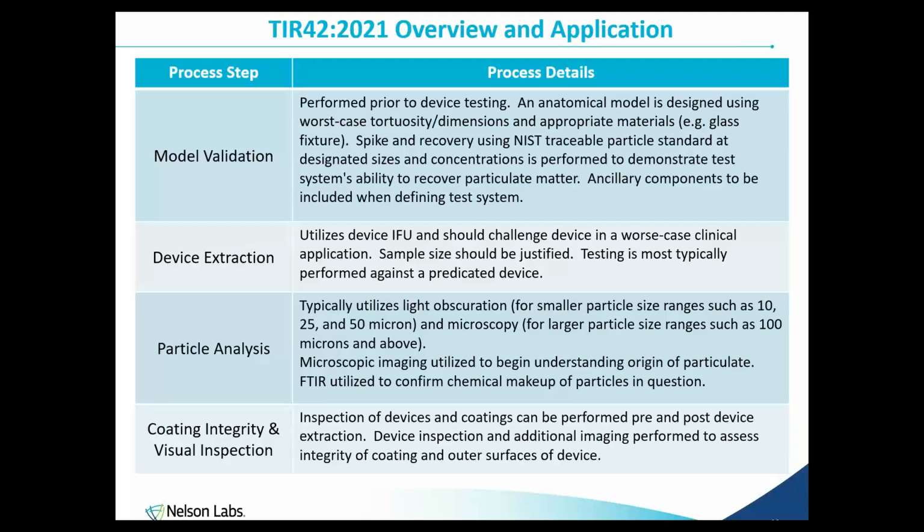that's typically a better way to make sure you're capturing all of those larger, more dense particles that during analysis, if you're using something like a HIAC system, could settle towards the bottom of a collection container. So the microscopic method allows you to capture those larger particles. And then you can go beyond that by performing some imaging, like in the last slide. And at that point, you've isolated the particles on a slide such that you can move on to further identification, so something like FTIR or SEM.